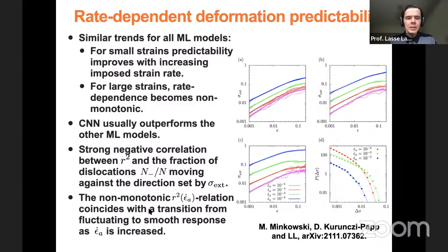Well, then we can also look at this non-monotonic behavior for large strains. That we think is related to a transition from fluctuating deformation dynamics to smooth deformation dynamics as you increase the strain rate. So for small strain rates, you have typically these fluctuating stress-strain curves with some stress drops and dislocation avalanches in the background, while for larger strain rates, you get smooth stress-strain curves. And there's a transition between the two as you increase the strain rate.